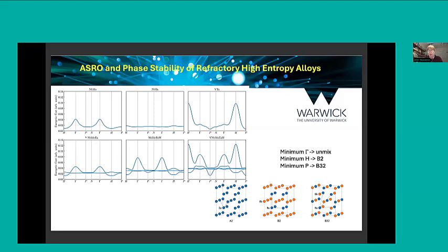When we go to the higher components, the 3, 4, and 5 components, again, we have a similar sort of picture. So niobium, molybdenum, and tantalum, this will have some B2, some cesium chloride type ordering at some temperature. And we can do some mode analysis, which I'll show in a minute, to show the nature of that ordering. Niobium, moly, tantalum, tungsten also has a B2 type ordering, and I'll show the analysis of the mode. But when some vanadium is added in, that promotes this B32 order.